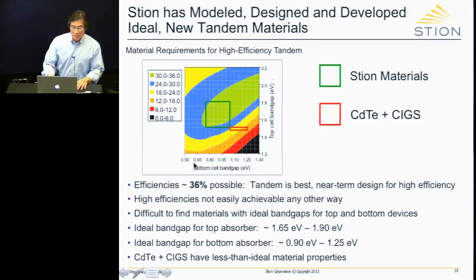This is the band gap of the bottom device, and this is the band gap of the top device. It's meant to be a three-dimensional contour plot. So coming out of the page, these different colors represent the efficiency of the tandem. And these are the efficiencies for the different colors. Clearly, you want to be in the green region, where the efficiency is about 30 to 36%. That's because we're taking into account other things that we can best model, things of the kind of recombination, for example, and real-life sheet resistances and things of that kind.